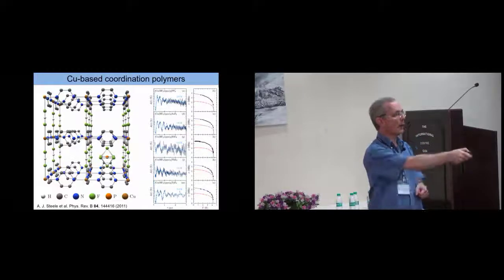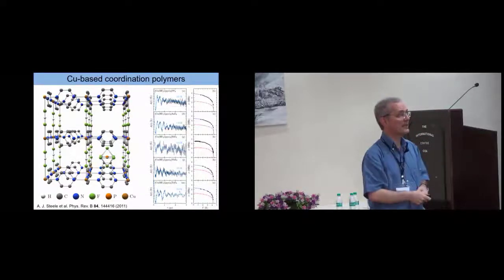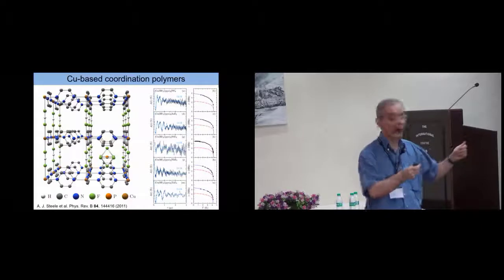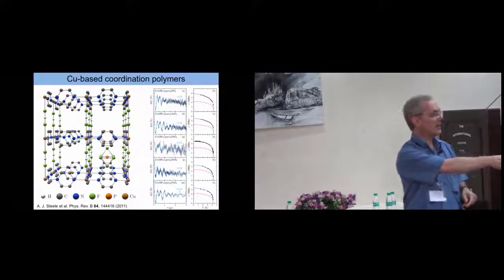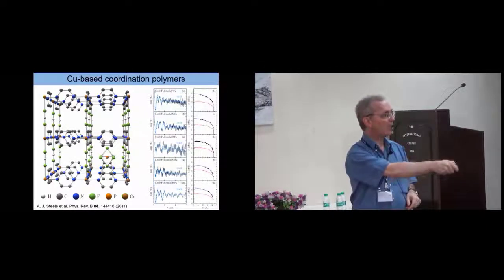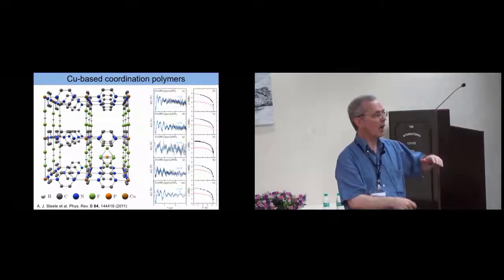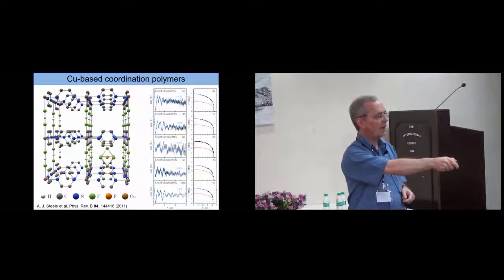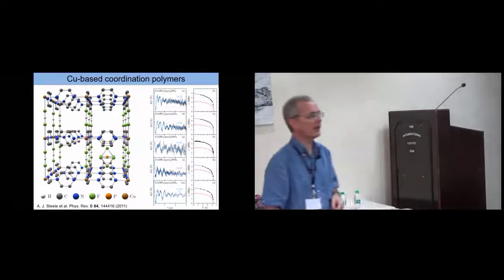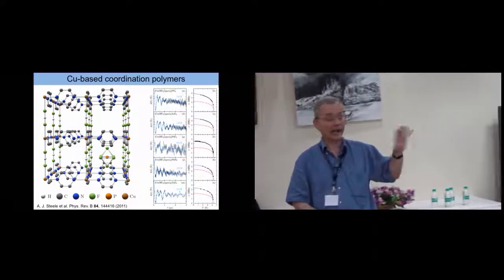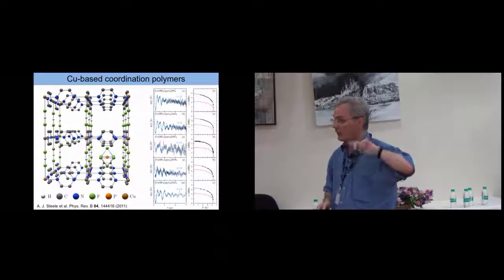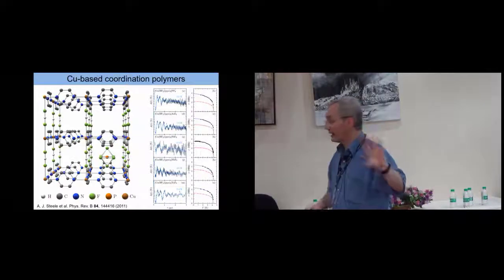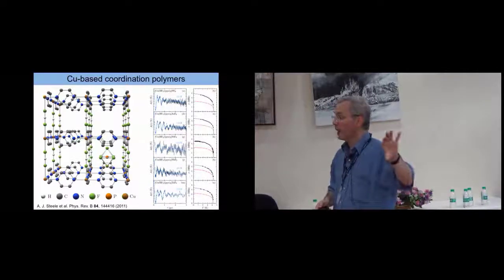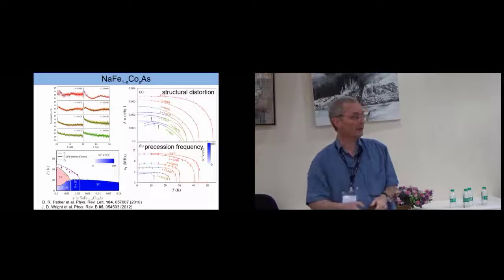One other example, these are some organic materials where you have copper ions that have a spin. They're linked together with organic groups, and actually you can just change the organic groups and make lots of different compounds. And here you can just see a whole lot of different compounds. Again, you can see the internal fields measured with μSR. And it turns out in these materials, it's very hard to measure the phase transition using heat capacity because they're low dimensional. μSR is the best technique for measuring them.